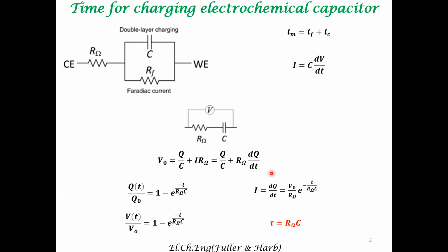But what is of importance to our discussion is this characteristic time constant relevant to the double layer capacitor, electrochemical double layer capacitors. So let's look at this expression. This time constant is greater if the capacitance is greater. That makes sense, right? If the capacitance is larger, that is, there are a lot of binding sites at the electrode surface for the ions to bind, then it will take a larger time to charge that interface. And in addition, if the resistance to transport of the ions from the bulk or near surface to the surface is greater, then the time constant for charging will also be larger. So physically also, this formula of tau, the characteristic time constant of this capacitor, being related to R omega times C, makes sense.